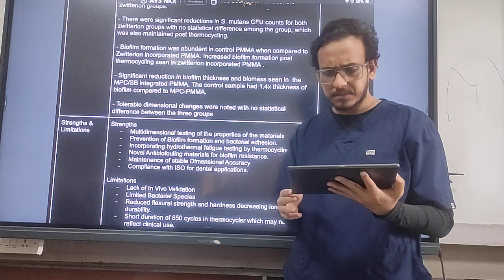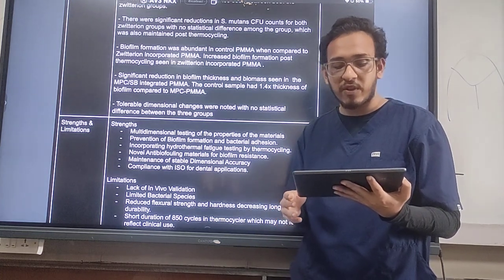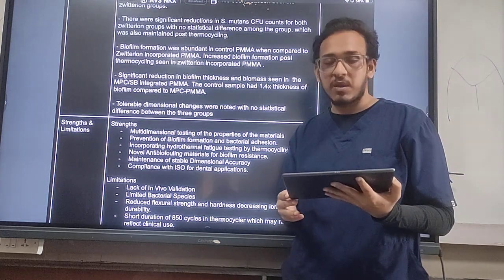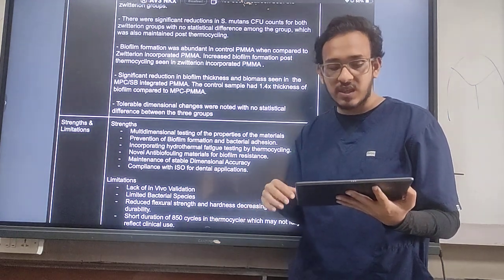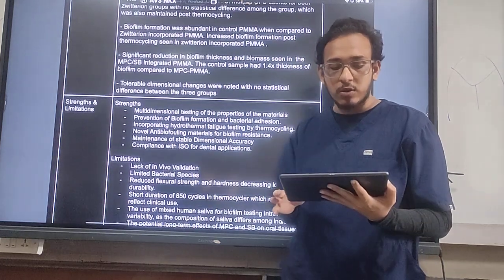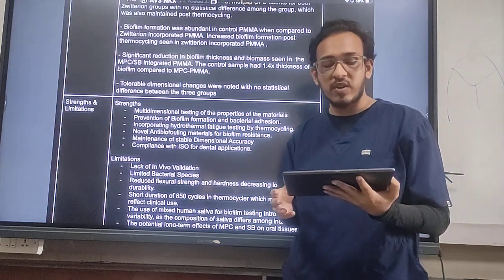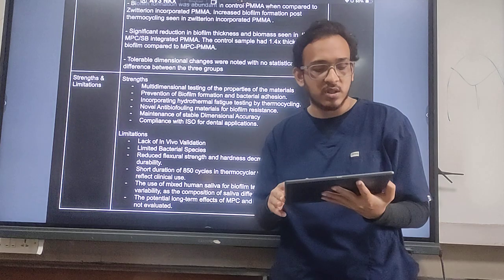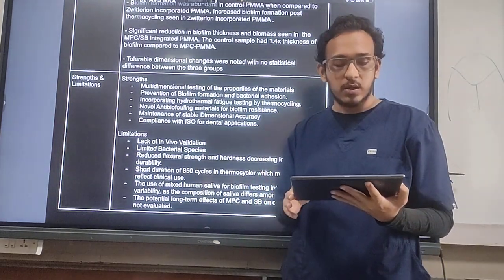The control sample had 1.4 times the thickness of the biofilm compared to the MPC PMMA, which means the Zwitterion incorporated PMMA had less thickness compared to the PMMA without the Zwitterion. Also, tolerable dimension changes were noted with no statistical difference between all the three groups after thermocycling. So there were no significant dimensional changes noticed in the three groups.